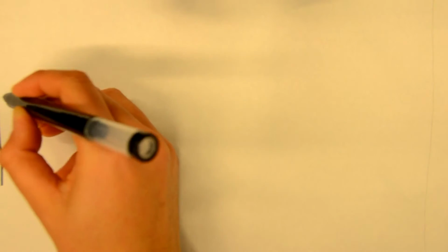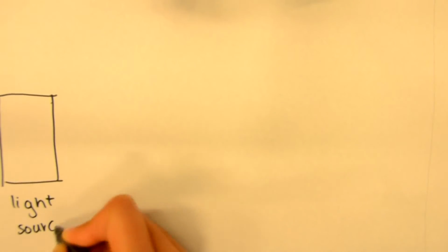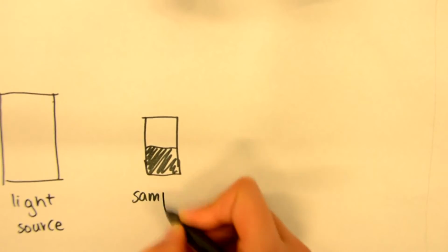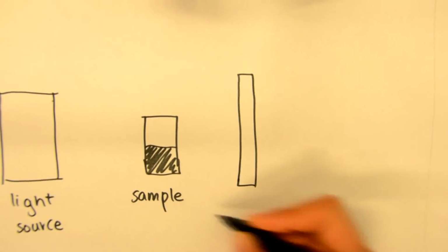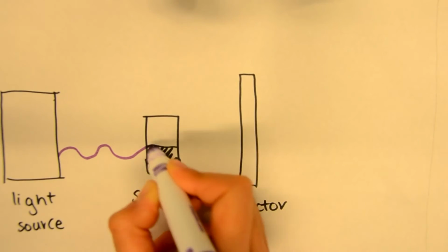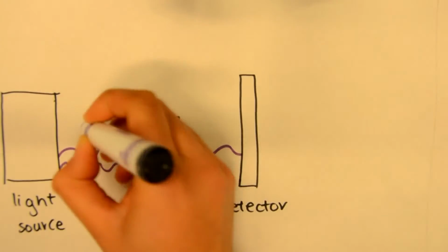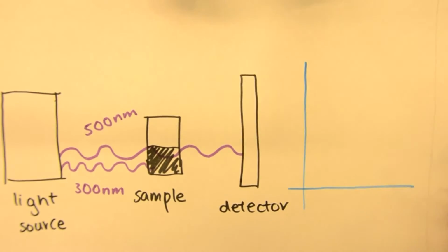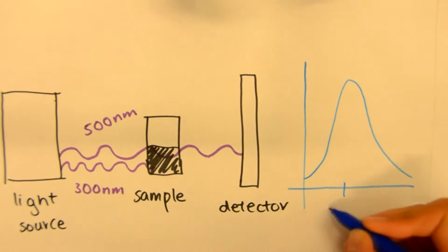An estimation of the size, and thus the color, of nanoparticles of a known shape can be obtained by measuring the maximum wavelength from their absorbance spectrum using a spectrophotometer. Radiant energy of selected wavelength is directed at a sample, and this machine measures what wavelength the solution absorbs the most light energy, and then it displays a spectrum.